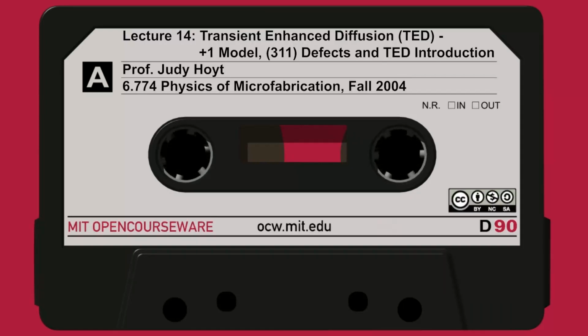I think I showed this last time, cross-section TEM. We're going to talk about this case on slide number 2, when the dose and the mass are high enough to amorphize the silicon. And these are cross-section transmission electron micrograph images of a sample that has been ion implanted and amorphized, and then is being regrown by putting it in a furnace at 525 degrees C. The initial implant was 200 keV of antimony. And look at the antimony dose, quite high, 6 times 10 to the 15th per square centimeter.